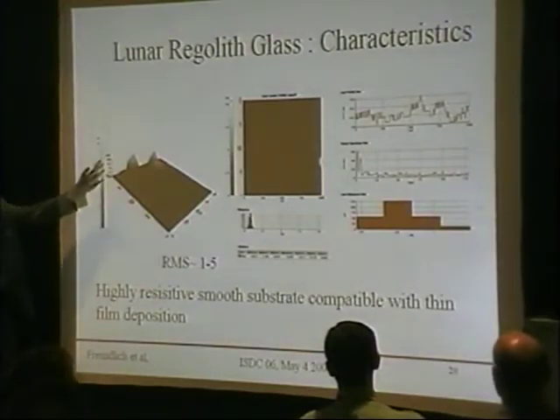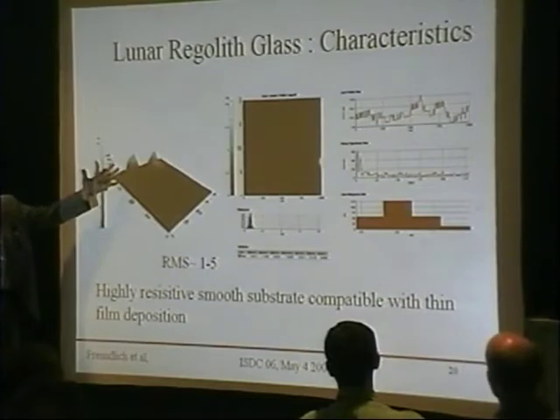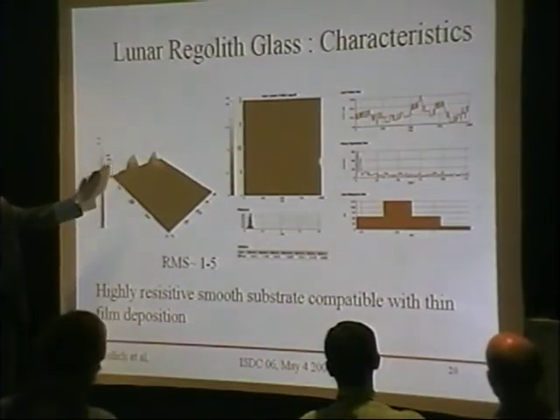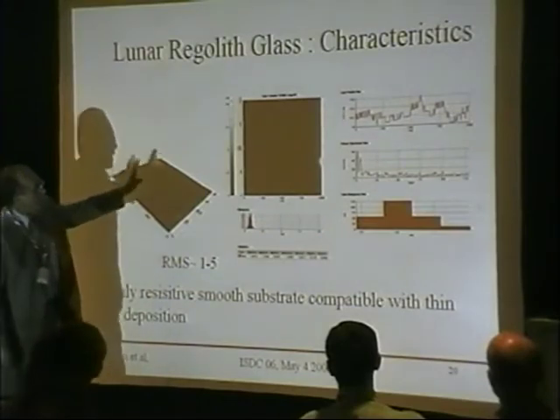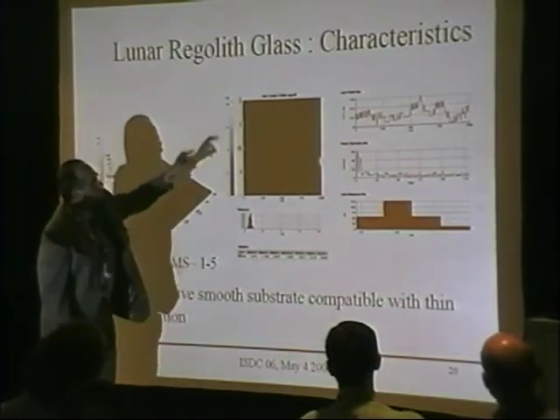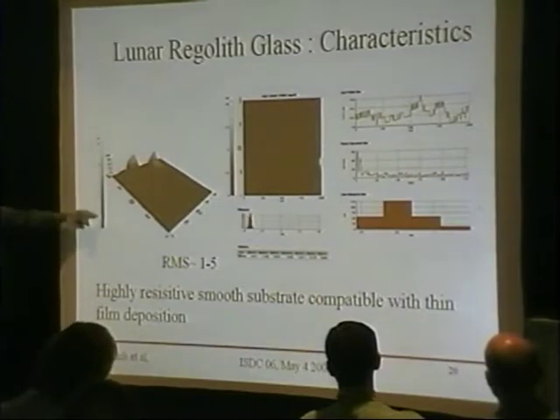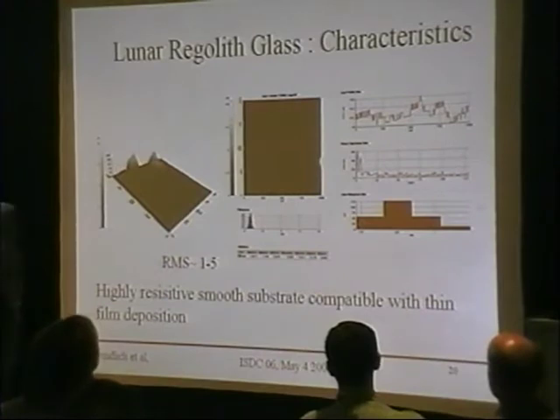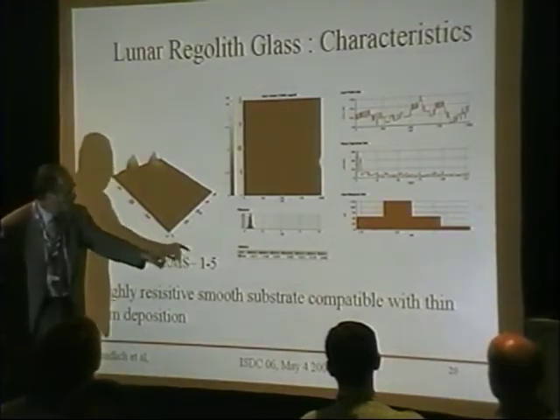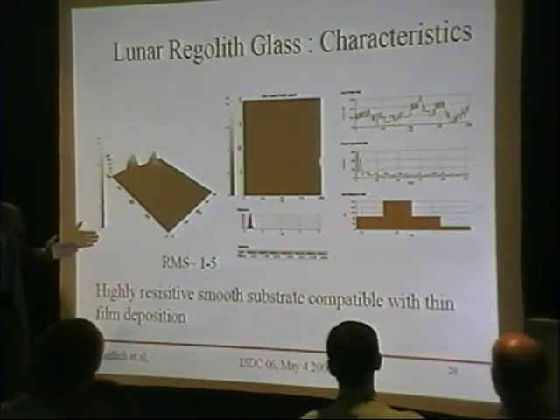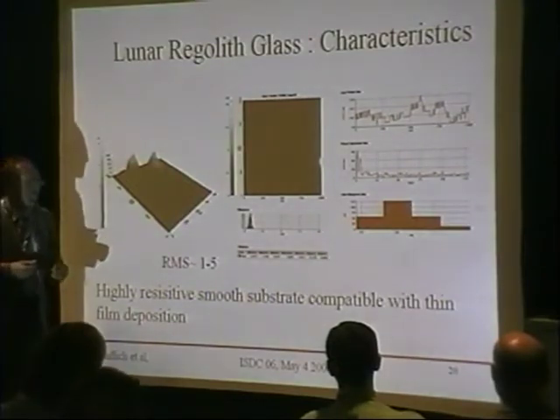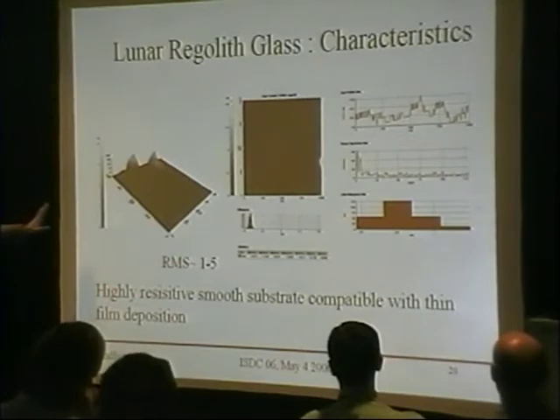Now, to show you how smooth this glass is, this is a picture generated through an atomic force microscopy scan. We scanned an area of about a micron by a micron, looking for defects. Things are not to scale; here we have 12 nanometers. The RMS roughness we found was between 1 and 5 nanometers on the areas we checked. There are occasionally very big intrusions, because sometimes a rock of 10 micron passes through, but essentially it gives you a relatively smooth surface with a very high resistivity. Next.